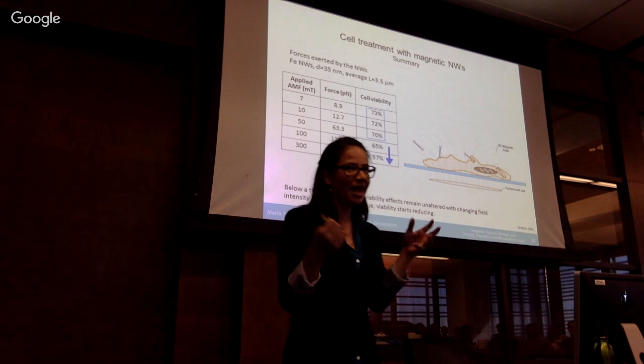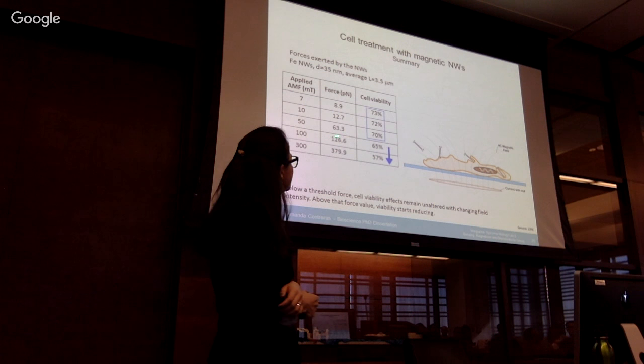Interestingly enough, there was a publication in 91 that estimated the force needed to mechanically disrupt the membrane of the cells, and this force value is around 100 piconewtons, which falls into this threshold. So we do have a threshold force in which viability remains unaltered when changing the intensity of the field. However, above this force, we start seeing an increased cell death.